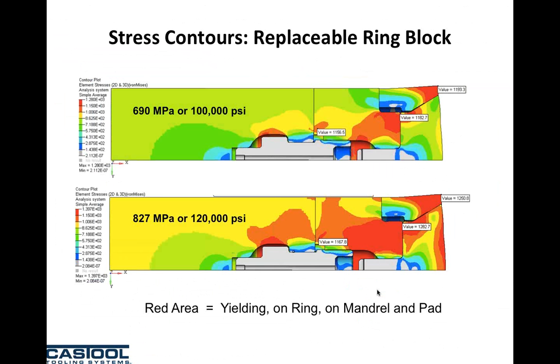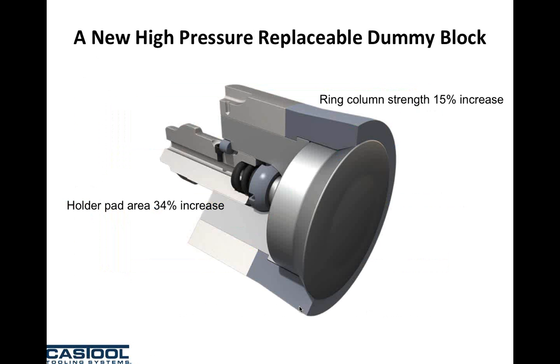Now we increase the pressure, the specific pressure the dummy block sees, and you can see on this study, the top one is around 100,000 psi. You start to see some red areas, which the block is starting to yield. When you increase by 20%, which with a longer billet, 120,000 psi, a lot of them became red. So red means the block is yielded, and so when you expand, the nominal diameter of the dummy block is going to be different, and it's going to be collapsed differently as well. So then we need to come up with a new dummy block that can withstand higher pressure. So we increase the column strength by 15%, rear column strength, and the pad area by 34% to withstand the higher pressure that we just mentioned.